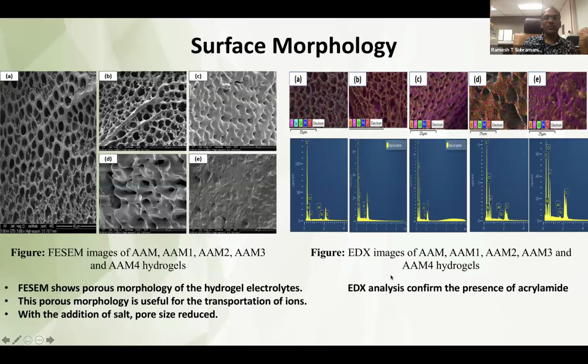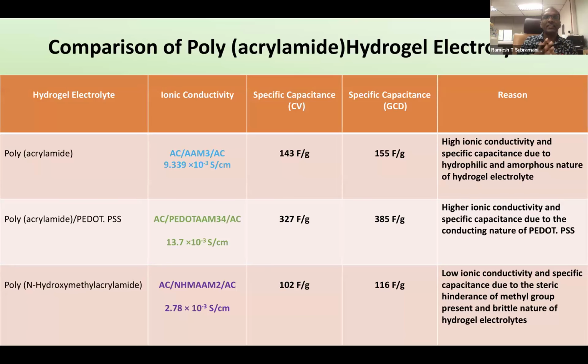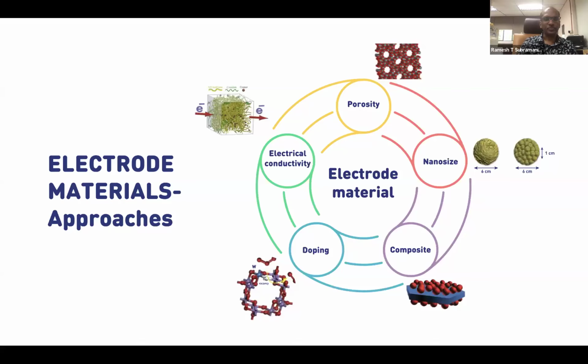They show the porous morphology of the hydrogel electrolyte. So these are very useful for the transportation of ions. And EDX also confirms the presence of acrylamide in the materials. The hydrogel electrolyte results show that the modified polyacrylamide, with a branch chain and with another conducting polymer added, will show better performance compared to the pure polyacrylamide hydrogel electrolyte.